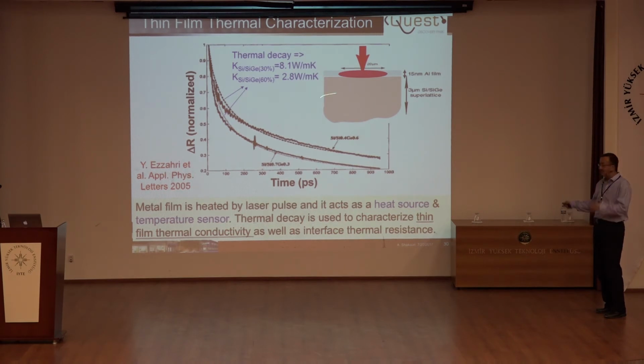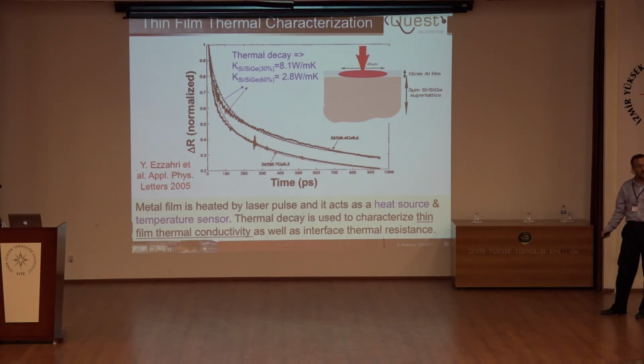Then the heat is dissipated, only going down. There is no other place for the heat to go. So the sample reflection, which is a measure of temperature, increases at time t equals 0, and then decreases. And here is our reflection versus time, here is 1,000 picosecond. It's very fast. You need a femtosecond laser to measure this. And what you see, 2 samples, one of them decays faster than the other.